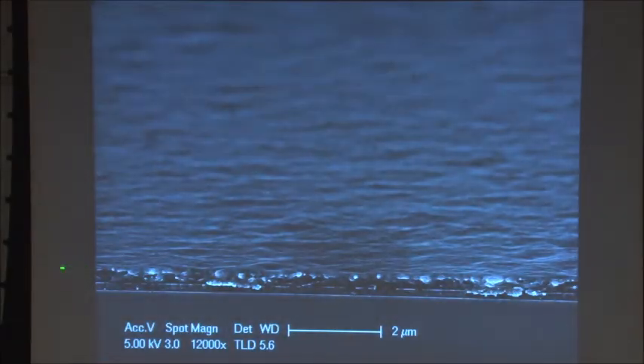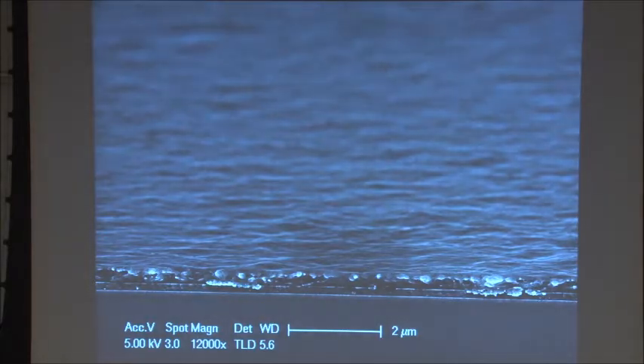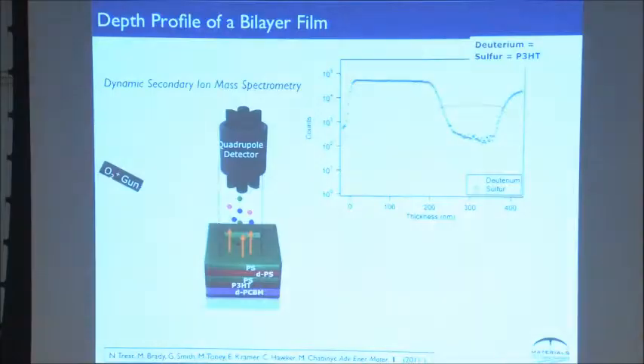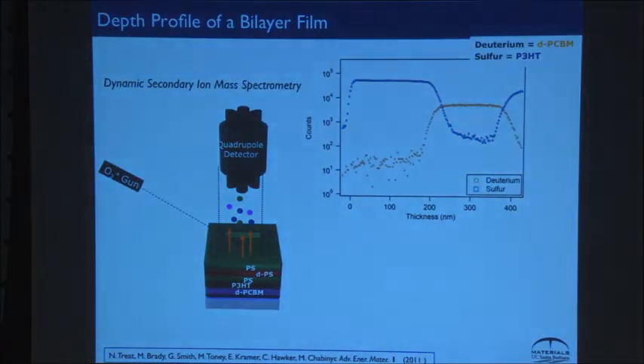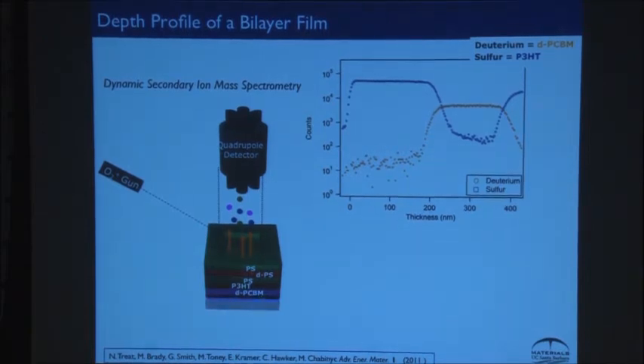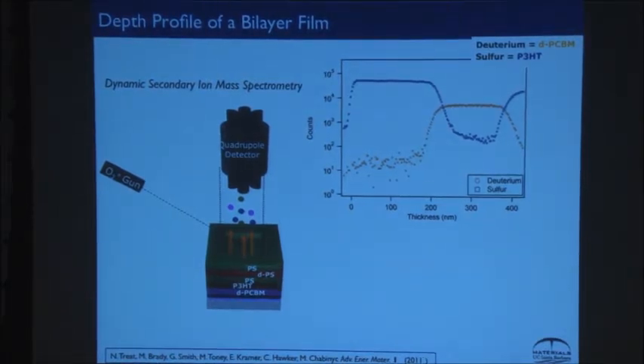And so we get a layer like this, where just to show you, this little ratty on the edges, we just break the wafer. It's fairly uniform. And what we do is then we take this carefully prepared sample, and the students then go off and destroy it. So they do dynamic SIMS. You look at this layer and you depth profile it by sending in ions with an oxygen gun and measuring the secondary ions coming off.